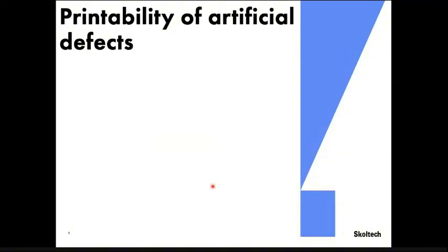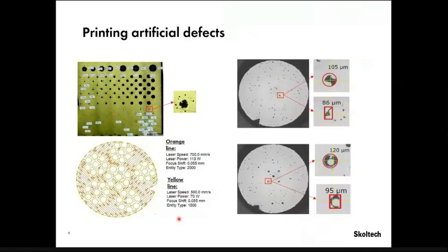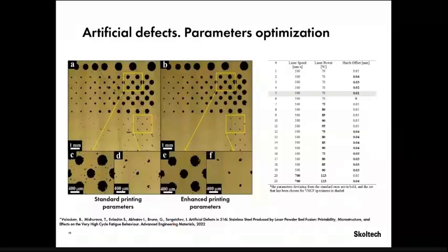First of all, we wanted to understand what we can actually print, which artificial defects we can print with our technology, our printers. For that reason, we first printed a prism with many through artificial defects of different diameters. We found that our artificial defects were surrounded by unwanted porosity, and we assumed that it was related to the contour parameters of the printer. We started to optimize them to minimize this unwanted porosity around the artificial defects. For that reason, we printed 21 such prisms with different contour parameters and found the regime which allows us to decrease this unwanted porosity in the vicinity of the artificial defects.